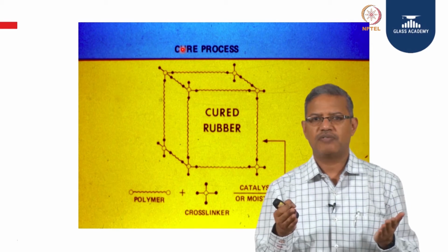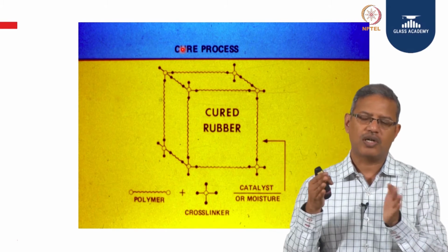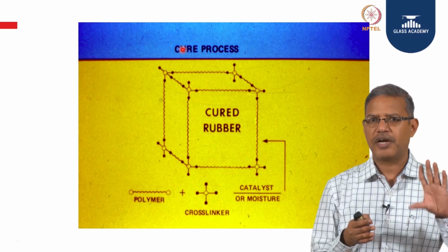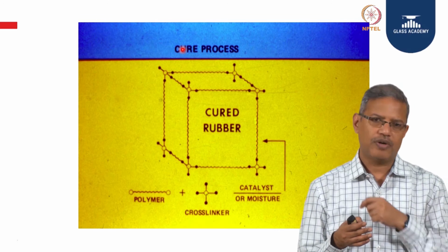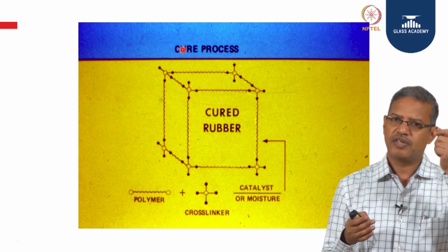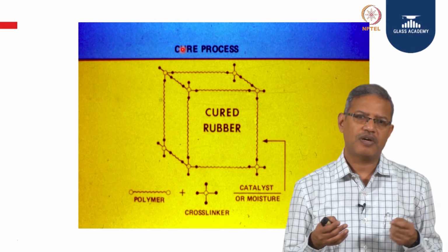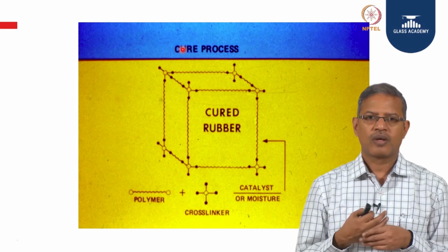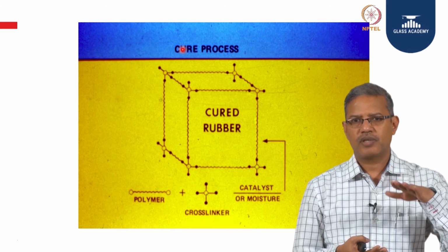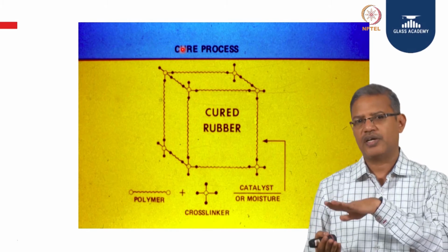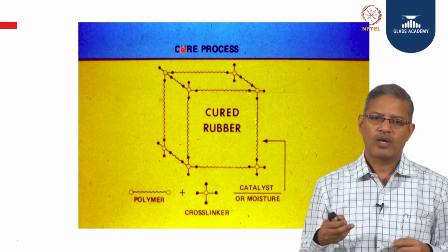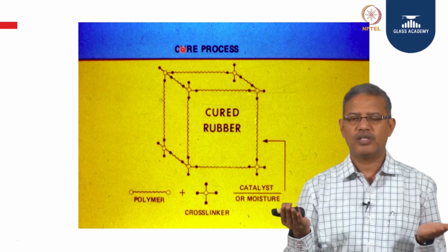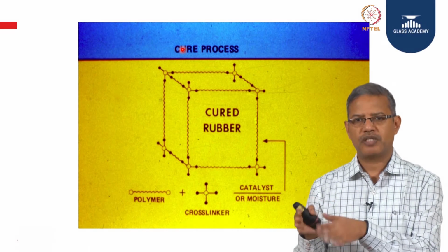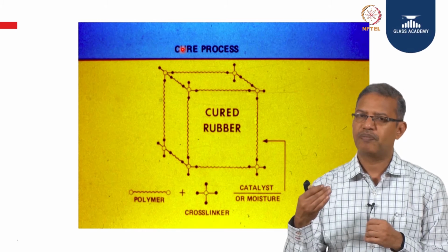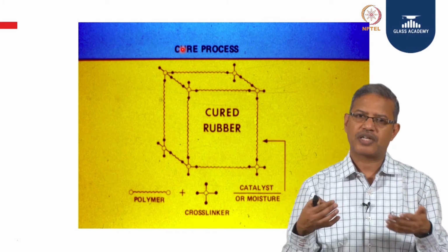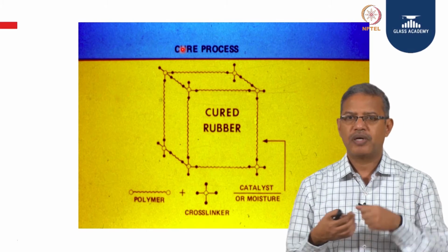There are two big classifications of sealant, one is called one part and the second is called two part. The one part is a ready made cartridge, you get it in the market for your insight or some of the weather seal applications or some of the site applications where it is very easy to handle and apply. The two part comes in a big drum, like a 250 kg part A and a 19 kg part B. These two are mixed at a particular ratio and then applied. The difference between these two is actually the cure rate. The two part cures much faster because it does not require moisture to get in for cure. There is a catalytic reaction which happens wherein A and B react, but no byproduct needs to be released.